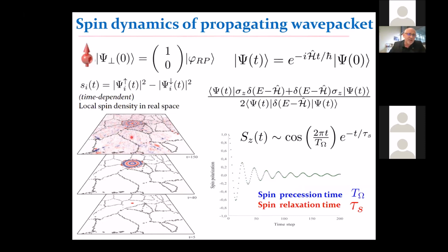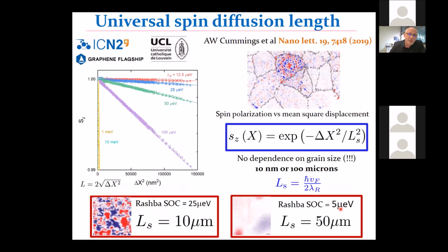Here is an example where we inject some electrons in the center of the sample with an out-of-plane spin polarization, and then it propagates in this polycrystalline sample with an additional effect of the in-plane Rashba due to the substrate. By looking at the dynamics, we are able to extract the spin relaxation time and the spin transport length scale. And it turned out, by doing this type of modeling, we were able to determine that there is actually a kind of universal spin diffusion length. It does not really depend on the average grain size of this polycrystalline sample, but it's completely driven by the strength of the spin orbit coupling induced by the substrate.